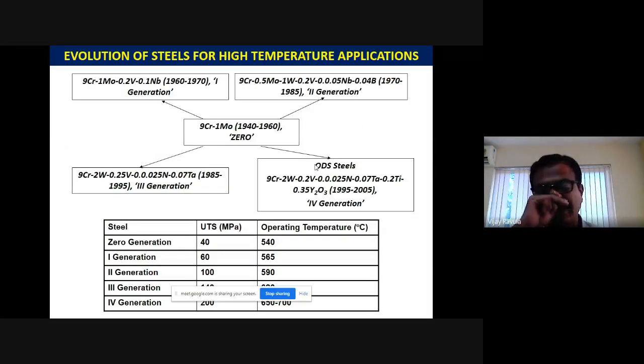And you can see the evolution of the steels, taking 9 chrome material as an example. In the 1960s to 70s, first generation steels had only solid solutions, and then moly, vanadium, and niobium were used. In the second generation, they also added boron and tungsten. In the third generation, they also added tantalum. They went from solid solution to precipitation strengthening, and then from 1995 to 2005, in the fourth generation, along with precipitation, the oxide dispersion. So that's why the strength goes up.